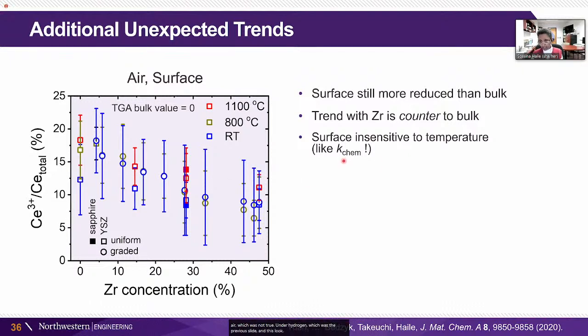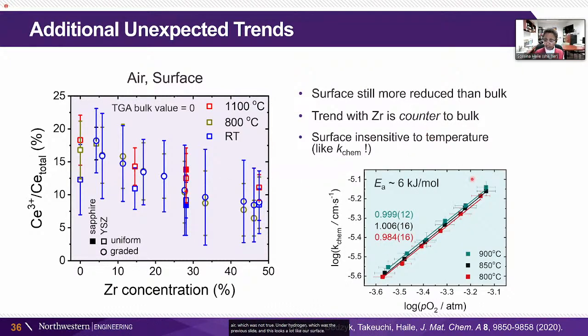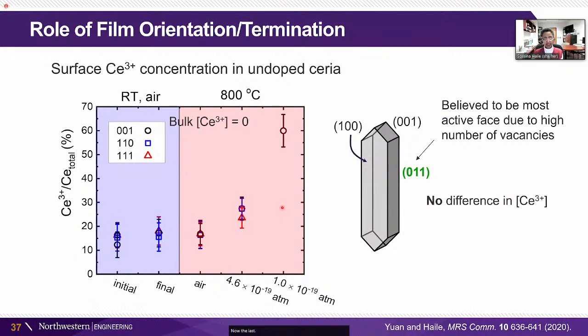And this looks a lot like our surface reaction rate dependence. This is also under moderately oxidizing conditions. And we saw that there was not much temperature dependence at all here. So this 900, 850, and 800 look almost the same. Here, of course, we have a much wider temperature range, but it just doesn't seem to be temperature sensitive, which is quite anomalous. Now, the last piece is the difference in terminations.